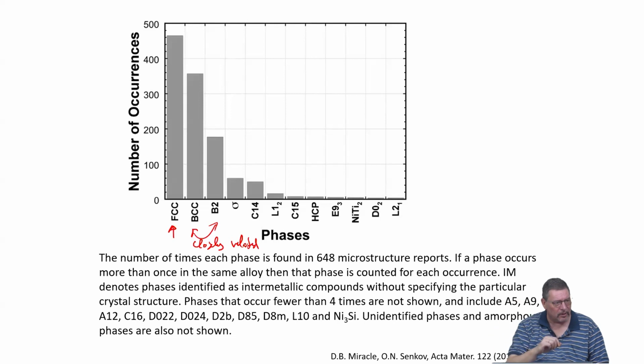It's a very hand-waving concept where you basically say, I take in alloying elements and they have in their natural single element case a preferred structure. That's the structure in if I add this element. And this will most likely, especially if I add several elements that prefer or have the same structure in, result in structure out in the phase or structure of the phase of the solid solution that forms when mixing them. And so this structure in, structure out kind of thinking seems to be fulfilled for many high entropy systems.